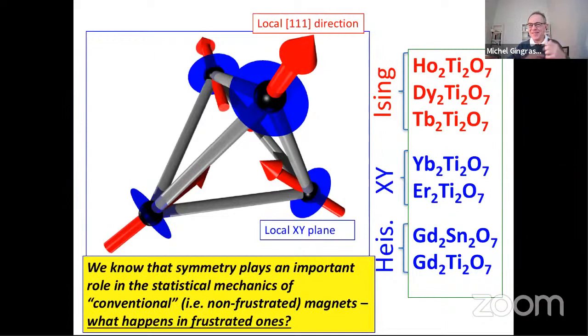So Daniel, you very much know all about this. Holmium has to have an Ising ground state because it's non-Kramers. Dysprosium is a bit of a consequence of the point group symmetry here, that this Kramers ion is Ising-like. Okay. So moving on.